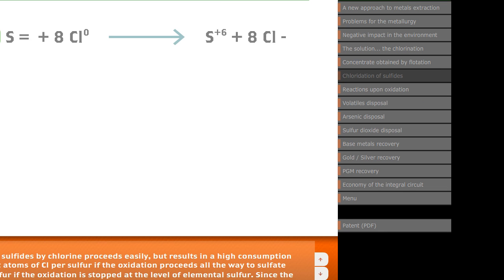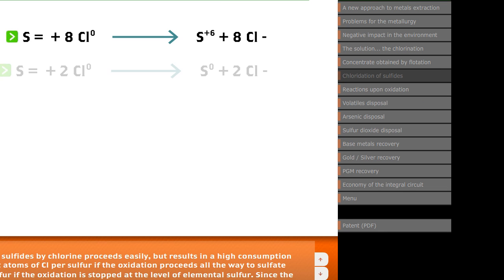The oxidation of sulfides by chlorine proceeds easily, but results in a high consumption of chlorine. 8 atoms of Cl per sulfur if the oxidation proceeds all the way to sulfate, or 2 Cl per sulfur if the oxidation is stopped at the level of elemental sulfur. Since the sulfur in the sulfide concentrate will vary from 15 to 25%, it will be readily understood that chlorine oxidation is uneconomical.